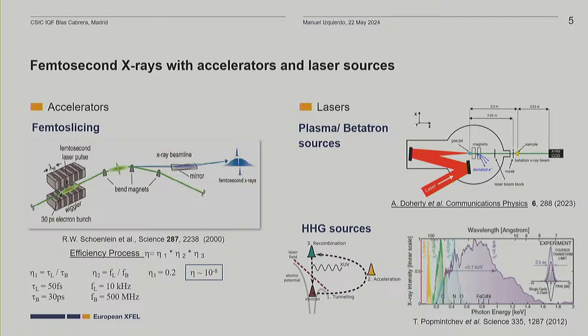Accelerators, on the other hand, did something similar. They went into the femtosecond regime by using a technique called femtoslicing. The femtoslicing technique is based on the fact that if you have an electron propagating in an undulator, and you make an interaction with a very powerful optical laser, you introduce a modulation of the electronic density, and you will create these wings in your electron bunch with a duration of femtoseconds, and the radiation that they produce will be in the femtosecond regime. This was demonstrated in 2000, and it has been used since.